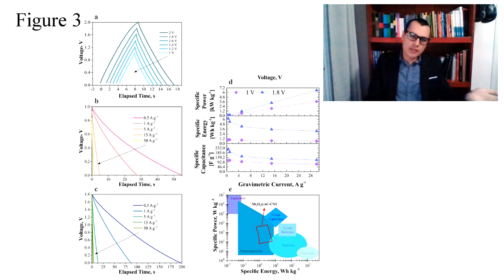So, lastly, in summary, the electrodes presented here have high stability in the aqueous medium, being able to be studied through electrochemical techniques. When tested in electrochemical cells, these materials showed high stability during 250,000 cycles of charge and discharge at a high potential window of 1.8 volts.